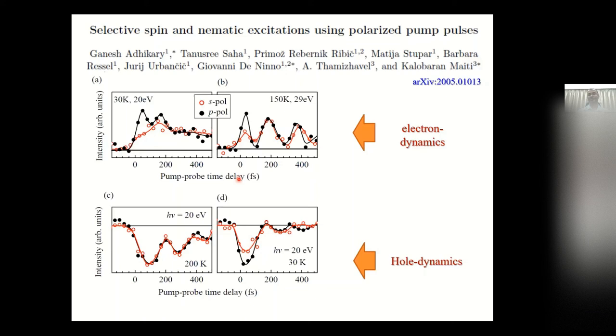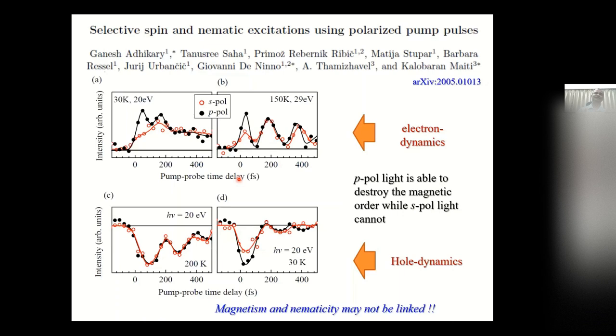From these observations, we think that maybe the magnetism and nematicity we are observing may not be linked. One could link this observation to the properties shown earlier — often in many systems, the magnetic ordering temperature and structural ordering temperature may not come together, and you can actually separate them significantly by applying pressure or other means. This shows that this kind of selectivity is actually real. You can determine an effective electron temperature using an effective distribution function, and we see that at 150 K in the paramagnetic phase, both polarizations are somewhat similar, but in the magnetically ordered phase you see a peak in P-polarization that is not present in S-polarization — essentially demonstrating orbital-selective heating where you are heating a subset of electrons using polarized light, which is not possible by any other method.